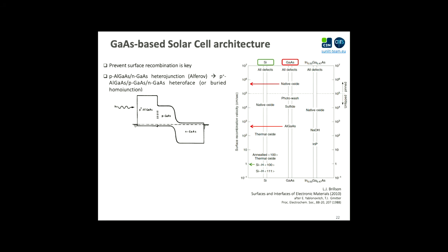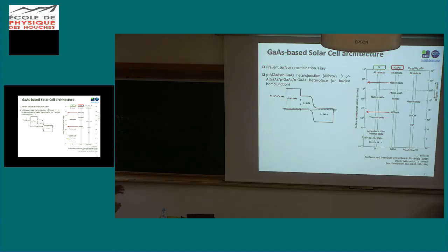So coming back to the gallium arsenide solar cell structure, the big deal for any solar cell, but in particular for gallium arsenide, is the surface recombination. And you can see it here. You have the surface recombination velocity for 3 different materials, but we will focus only on silicon and gallium arsenide. You see that already if you take silicon with some native oxide or gallium arsenide with native oxide, you have a very different recombination velocity, lower for the silicon.